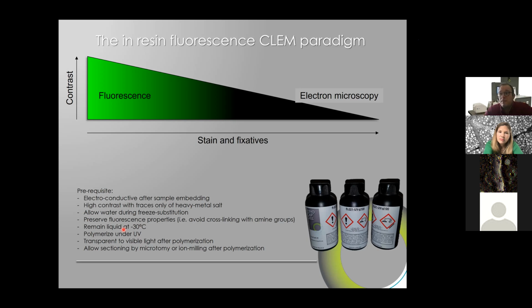Obviously, we wanted to have a very high contrast, and we could afford having some traces of contrasting agent, but that was not the only idea. If we need to have heavy metal salt, we use it, but that's an option. It should allow some water during freeze substitution, so it should have some hydrophilicity to some extent, because the papers before demonstrated that it increases the contrast, and the idea of the protein collapse remained valid for this study.